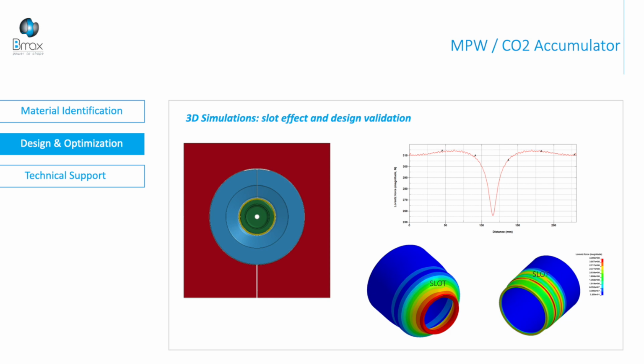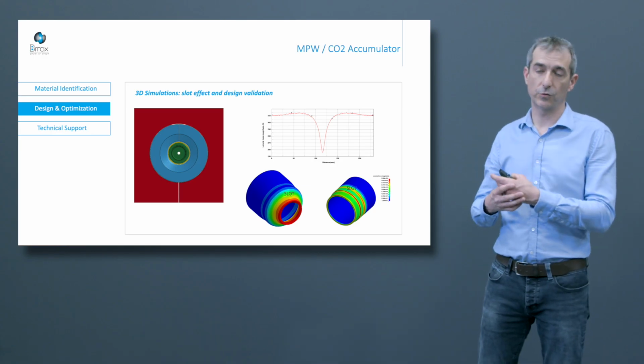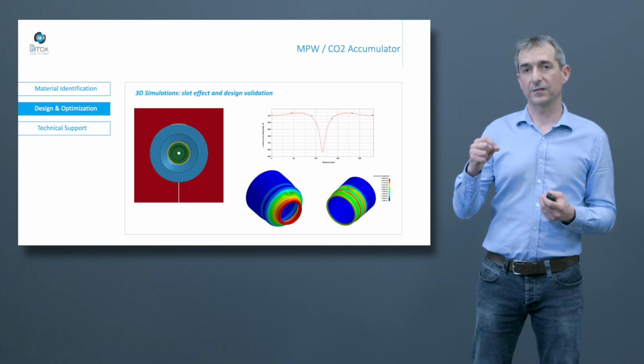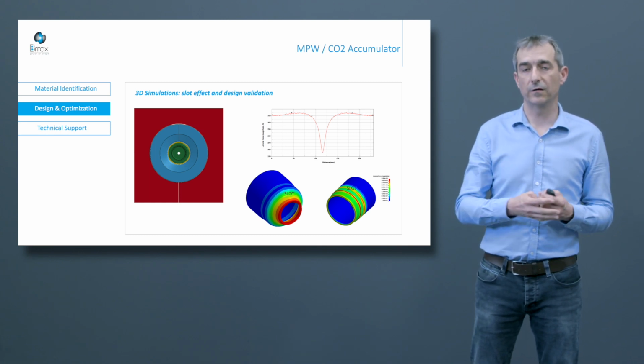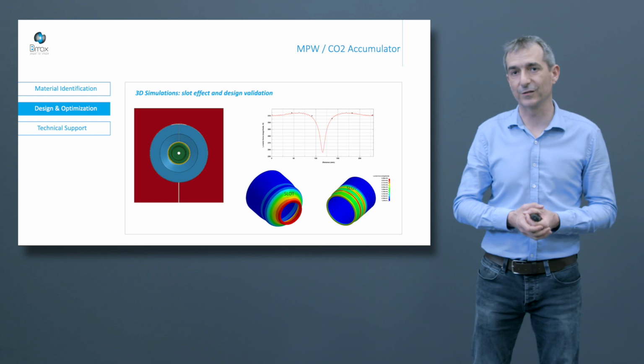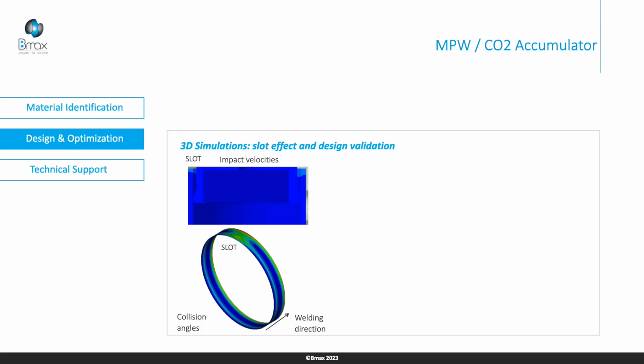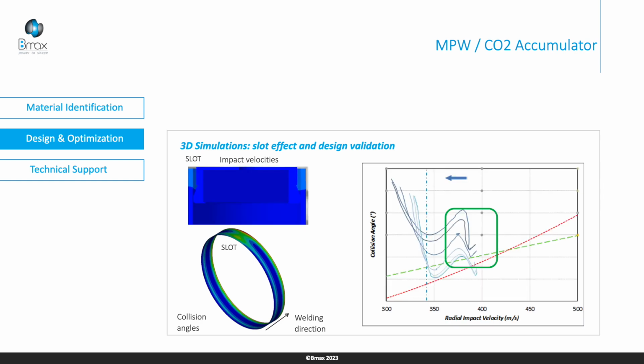and checking if we are in good condition at the slot area. Again, the slot area is where the current goes in and out. And this path of the current disturbs the magnetic field and the Lorentz force. As you can see in the drawing, the maximum Lorentz force decreased by 15%. So by 3D simulation, we'll check speed and angle to project this data on the welding windows.